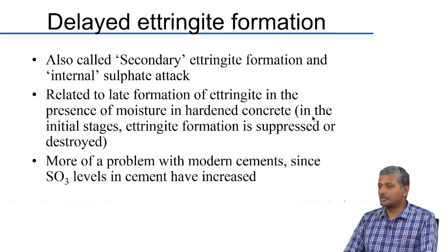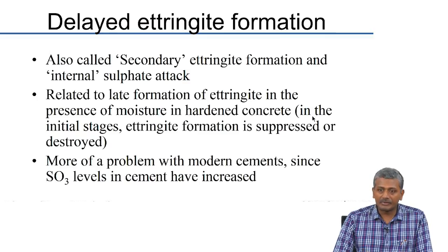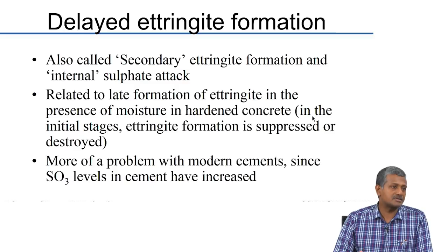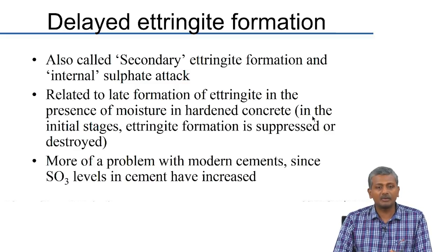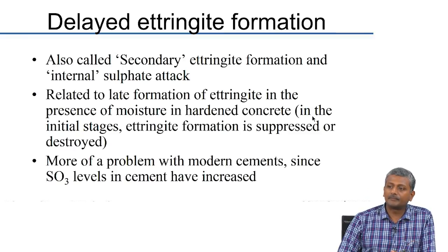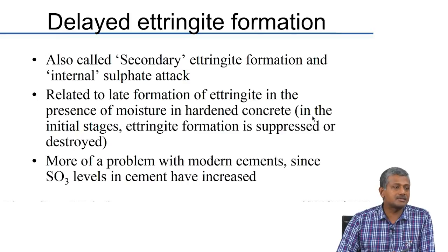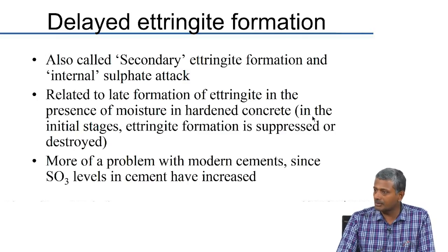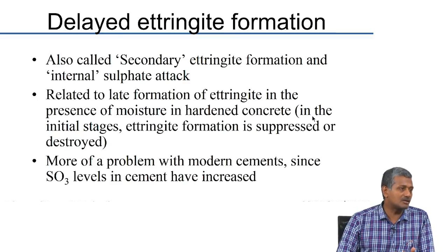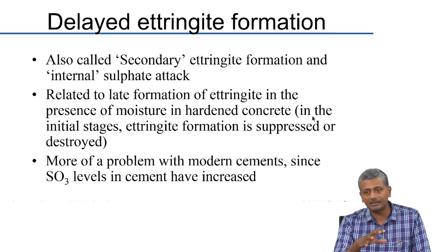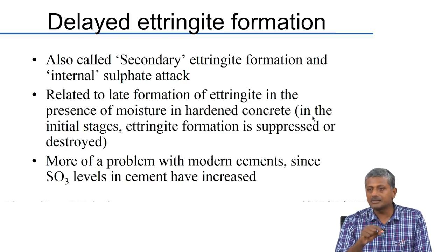Water-cement ratio is the primary factor determining sulphate resistance — not just the C3A level. A different type of sulphate attack is delayed ettringite formation (DEF). This was first investigated when some railway sleepers in the UK started showing cracks. Railway sleepers are produced in precast yards, typically pre-stressed precast, subjected to heat curing to increase the rate of strength development. These sleepers started showing map cracking or random cracking after about 15–20 years of service. Initially thought to be alkali-silica reactivity, but reactive aggregate was not found in the system. Microstructural analysis revealed a lot of ettringite forming and occupying the sites of cracks and voids.